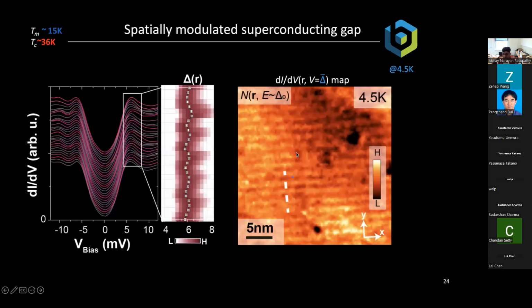And if you do that, I hope all of you can now see very clearly these unidirectional lines that run in this conductance map, which is basically visualizing the same thing. It is telling you that this superconducting gap is modulating in a sinusoidal fashion as I go across in this particular direction. Now, I should say right here that this does not fit the formula cosine of QR. If it fit cosine of QR, the gap should go to 0 somewhere. And clearly the gap does not go to 0 anywhere in space.